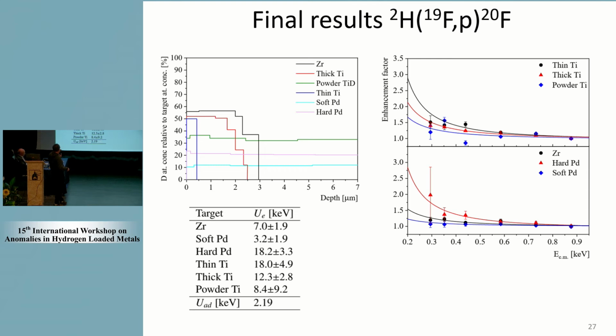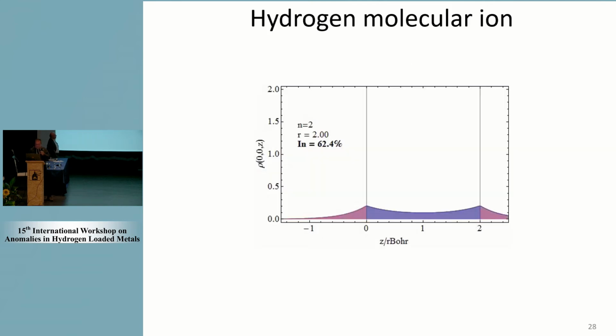Oh yeah, this powder titanium was produced in Dresden. They heated this powder to 700 degrees and then put it in a hydrogen atmosphere, so it had time to diffuse. This one is also inconclusive, so it could also be no electron screening. But you can see that different ways of preparing the targets give you different results. The most effort we spent on palladium; we don't know about titanium why we have different results in different titanium targets. So this is the last one that I wanted to show.